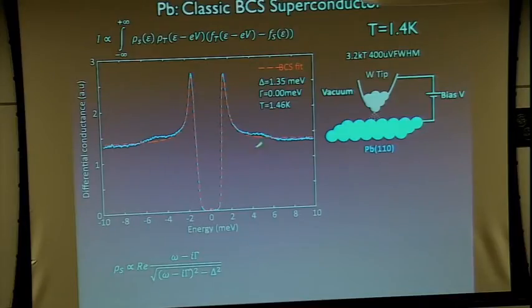And the analysis of these features in the 60s was actually the thing that allowed us to really quantitatively pin down BCS pairing for electron-phonon superconductors. You can back out from these features the spectrum of the phonon mediating pairing. So of course, lead has strong spin orbit coupling because it's a heavy element, but let's hold that thought, and I'll actually show you some very nice experimental evidence for that.